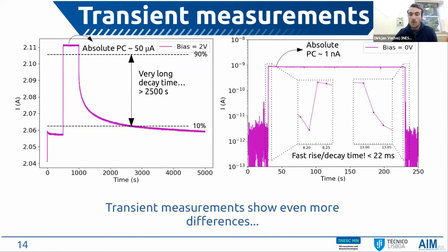Then when moving on to transient measurements, in these measurements we fix the applied bias and turn on the light at some point, and turn it off again at some point later in time, and then study the transient photocurrent. We can see that the differences are even more pronounced. So in the case of the n-type conductive device, we measure a very long decay time. In this case, it takes the device over 2,500 seconds to go from 90% to 10%, while in the case of the PN junction diode, the rise and decay times are actually below 22 milliseconds, which is again the measurement limit of our equipment.